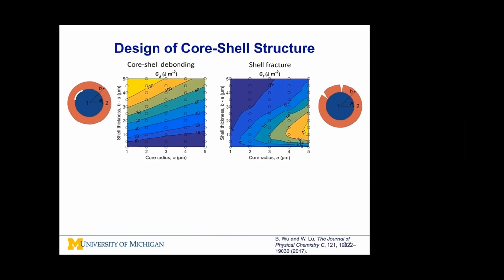Using active material particles with a core shell structure is an effective strategy to combine the advantages of two materials. However, two failure modes can happen to cause the structure to lose its integrity: delamination of the shell from the core, and fracture of the shell.